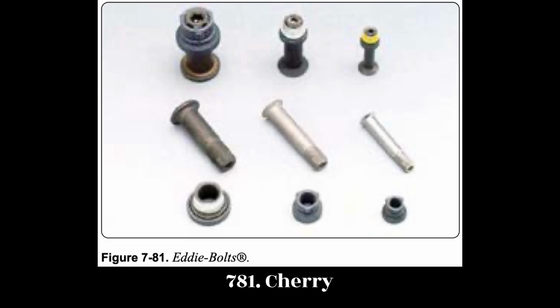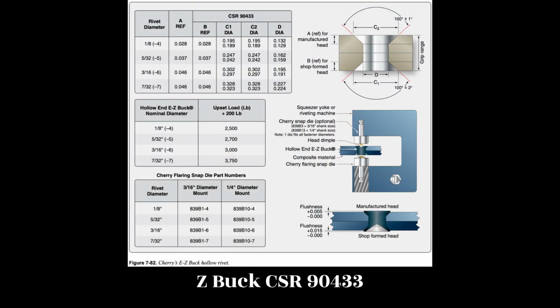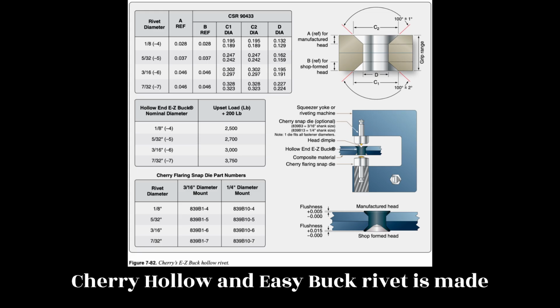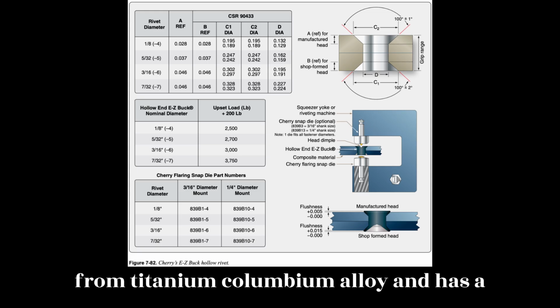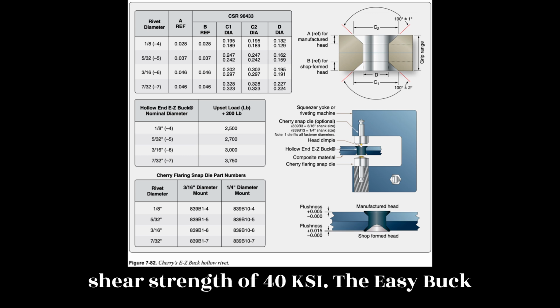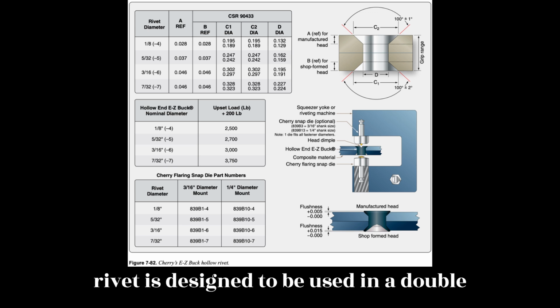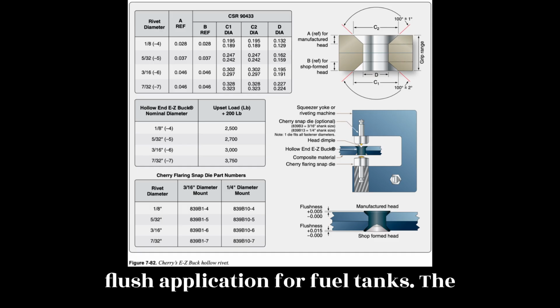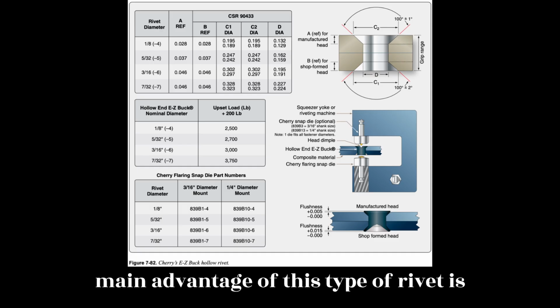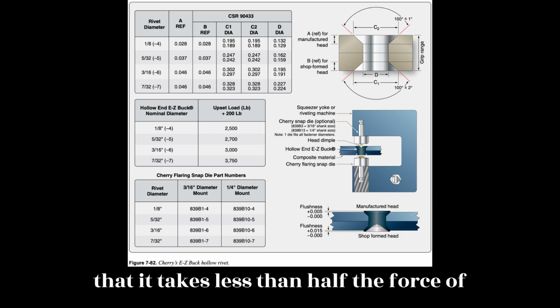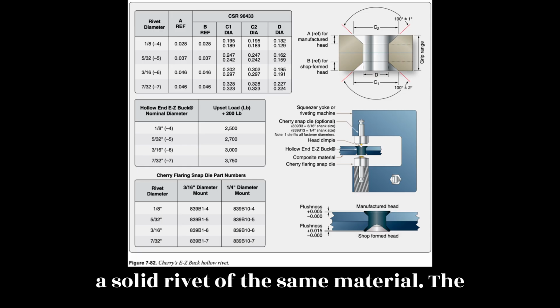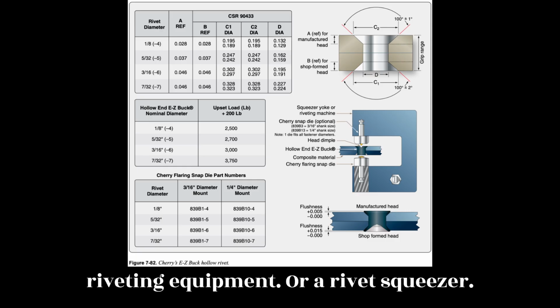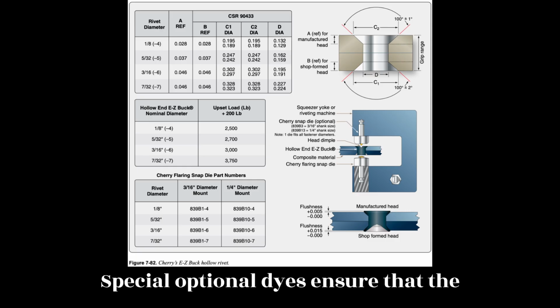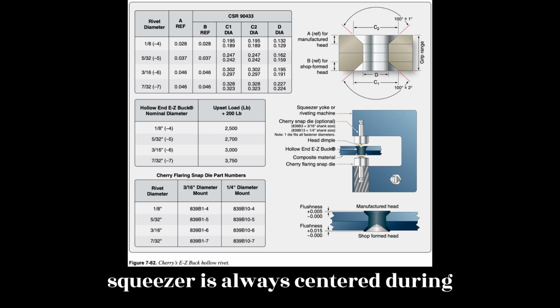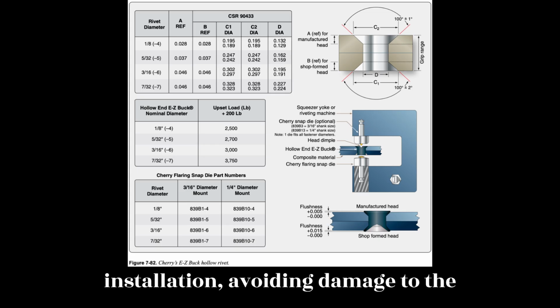Figure 7-82. Cherry E-Z Buck, CSR 90433, hollow rivet. The Cherry hollow E-Z Buck rivet is made from titanium/columbium alloy and has a shear strength of 40 ksi. The E-Z Buck rivet is designed to be used in a double flush application for fuel tanks. The main advantage of this type of rivet is that it takes less than half the force of a solid rivet of the same material. The rivets are installed with automated riveting equipment or a rivet squeezer. Special optional dies ensure that the squeezer is always centered during installation, avoiding damage to the structure.